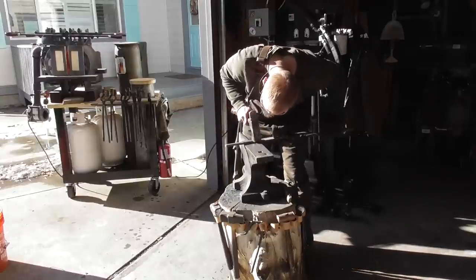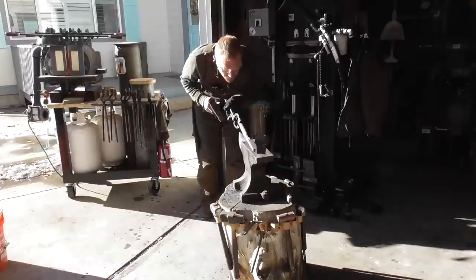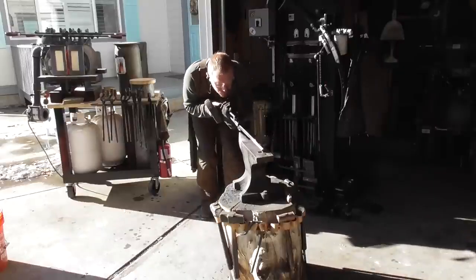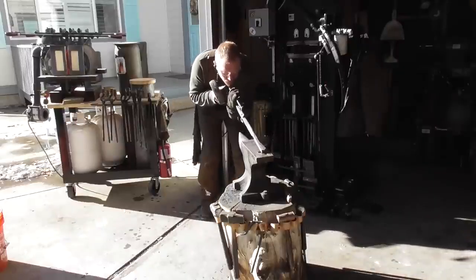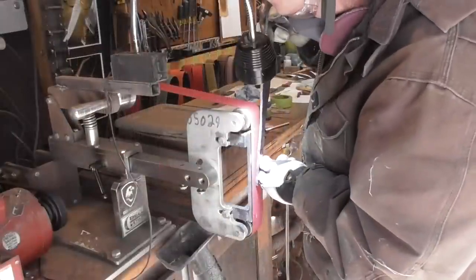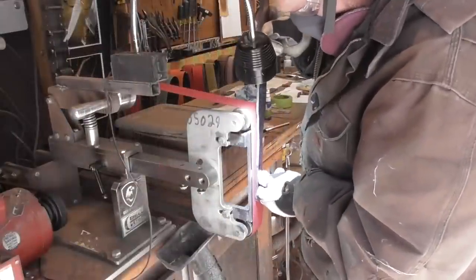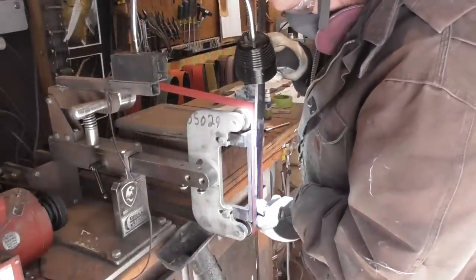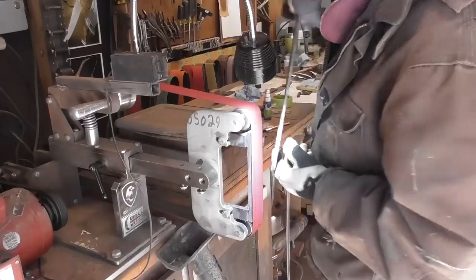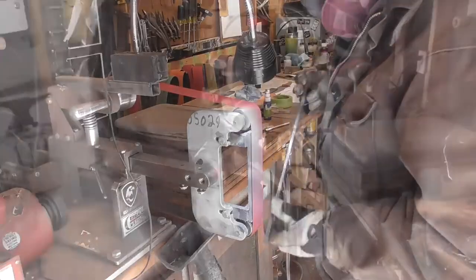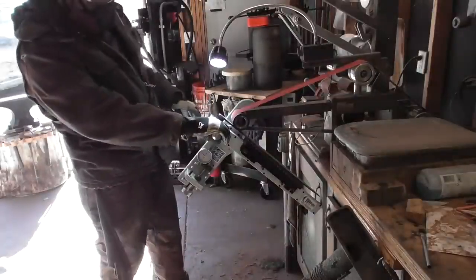Once all of the forging is complete, then I will take the blade through a normalization cycle, which is one round at 1600 degrees, one round at 1500 degrees, and one round at 1400 degrees for 5 minutes each. And that will just make sure all the steel is uniform and the grain structure is good. And once that's done, then it's time to begin to clean up the blade.